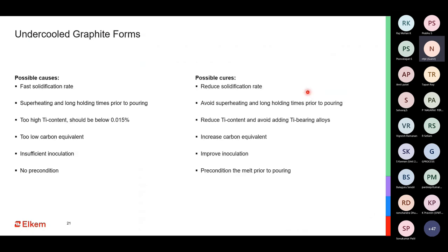A combination of undercooled graphites is one of the most common defects that we witness in our foundries. We have classified them as type B, which is the rosette. You can see this rosette kind of structure here. Type E, where you have a much more pronounced graphite dendrite structure and very little graphite precipitating around it. And then type D, where it is undercooled and directionally solidified, but you have a much higher graphite precipitation in the matrix.